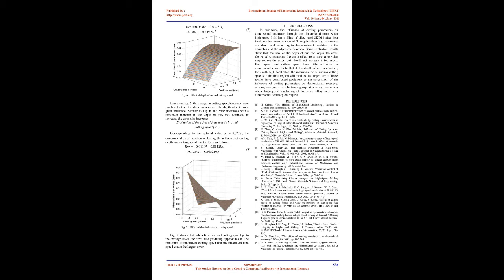is decreased. Because the error is gradually approaching 0, it is the best, but it will never reach the ideal 0. The error value approaches 0 when keeping the feed rate constant and gradually increasing the cutting depth, but only increasing to a moderate extent, near the 0 level. Further increasing this parameter will increase the error. Increasing the feed rate value does not have much effect on the dimensional error.